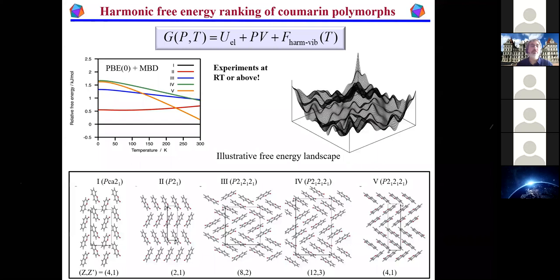And so there are going to be strong anharmonic effects. This is kind of becoming well known now, that at the experimentally relevant temperatures, this is going to happen. And this is a rigid molecule. Imagine what happens when you have something with some flexibility in it. Now, the difficulty with predicting free energies beyond the harmonic approximation, of course, is the fact that the potential energy that you're working with is a rough energy landscape, something we all know something about, right? You have lots of minima, lots of barriers, and so the difficulty of navigating over this creates what's called the rare event problem.